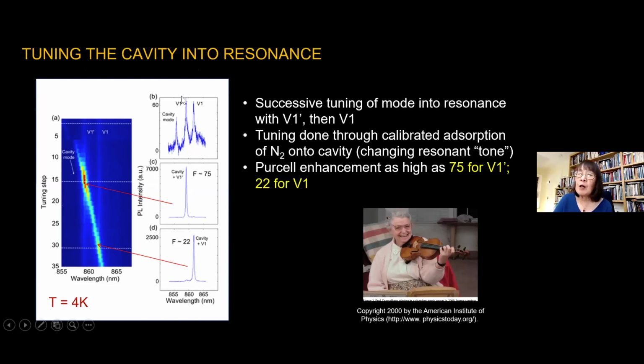If we go further to show the possibilities of this cavity, what I show you here is the cavity mode. So we're going to go the next step, and this is at a low temperature. This is not at room temperature. This is at 4 degrees Kelvin. And actually, what we see is that we can do better in picking out the unique signatures of the silicon vacancy. I told you about V1, V2. V1 actually has an excited state, which we call V1 prime.